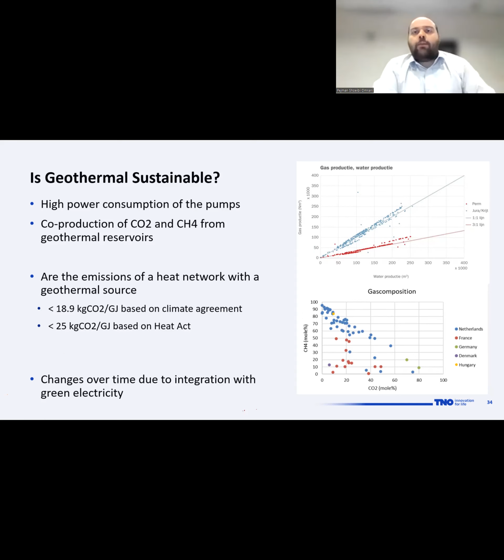For that, you always have to have some measures. We took two measures, one based on the climate agreement and the other based on the Heat Act, which says you have to go with this criterion of roughly between 20 to 25 kilograms of CO2 per gigajoule of the energy that you produce. And if you can achieve that by 2030, 2050, then you can say we meet this agreement that we have.